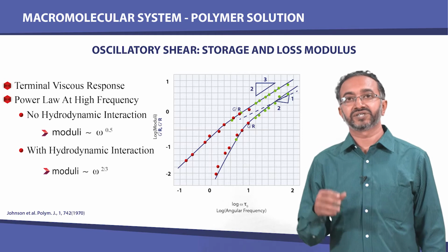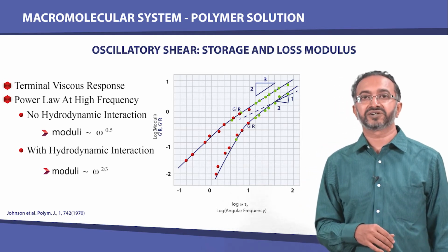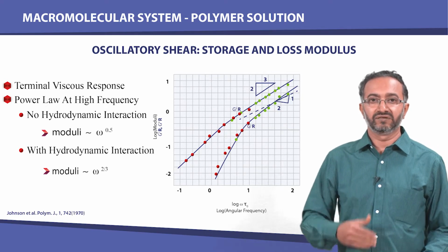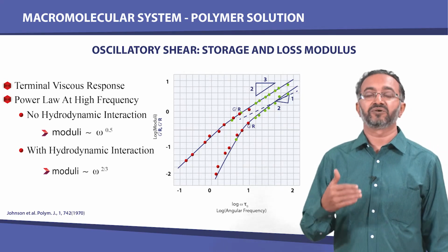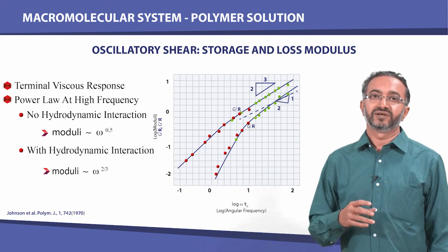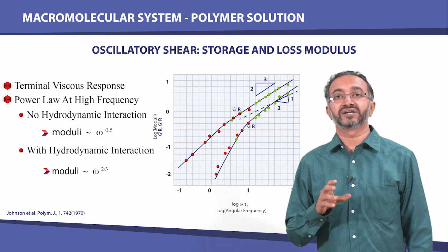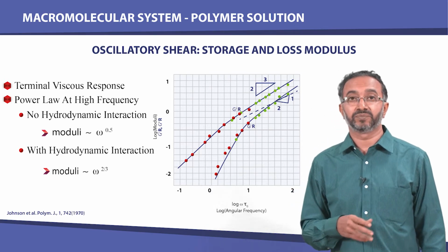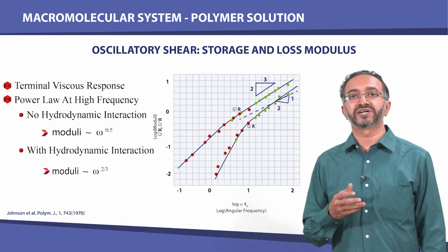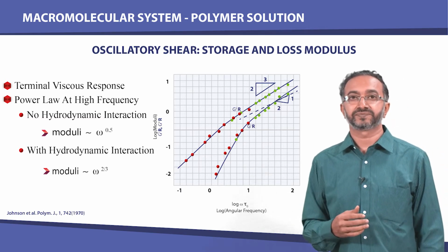So, the Zimm theory, which accounts for the hydrodynamic interactions, correctly predicts that both storage and loss moduli will vary with a power law dependence with a slope of 0.66. Therefore, we know that if we have to describe the polymer solution response at high frequencies, hydrodynamic interactions must be included.